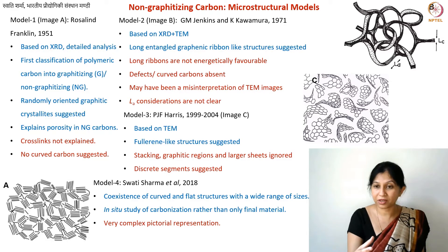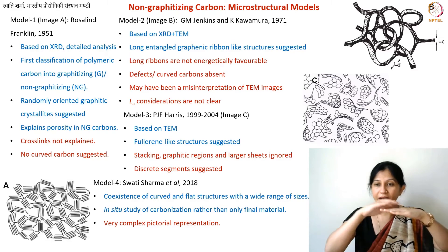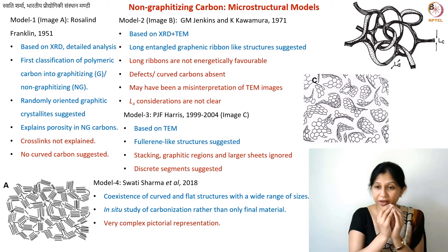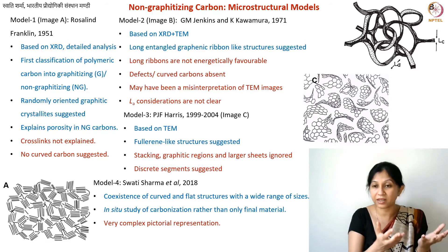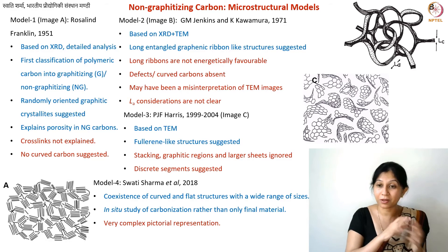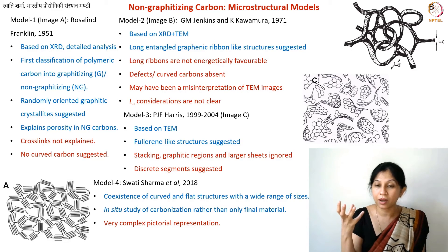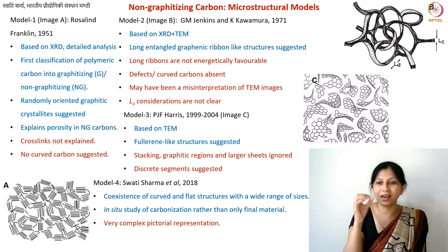Just imagine very long sheets which are flat, or curved, or parts flat and parts curved, and also certain spherical completely closed structures. This clearly explains the density and porosity — you definitely have closed pores and voids, clearly seen as fullerene-like closed structures. At the same time, you also have very long sheets responsible for electrical conductivity. You see pretty much all kinds of carbon structures in one place — and that material is called non-graphitizing carbon.